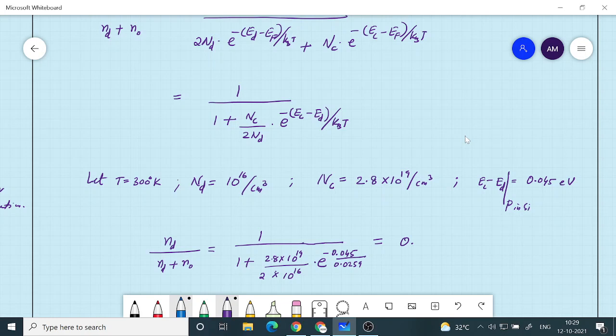So as you can see, it is e raised to minus 2, around e raised to minus 2. So e square will be something like maybe 6 or 7, but it is e raised to minus, so it is going to be a quantity smaller than 1. So this is already 1000, and 1000 will be divided by 1 by 7 roughly, so it is reasonably larger. It is something like 150, it will come around. So 1 divided by 150, around that it will come, and that will be obtained as 0.41 percent, which is very, very small.